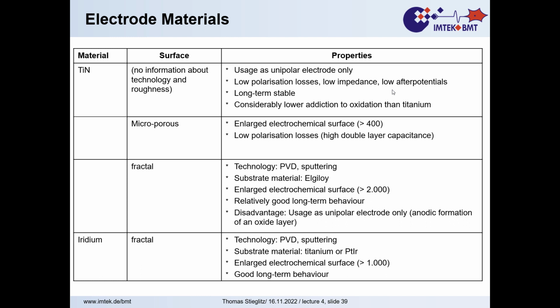And in micro machining, it's used in a way that you generate structures that look a bit like Giant's Causeway. So we have a kind of hexagonal pillars standing next to each other, and by that it increases the surface dramatically. Yeah, because you do not only have the surface, but you have the side walls of those pillars that contribute to the charge delivery. And if you imagine that as additional area for the Helmholtz capacitance layer, you get a lot more.